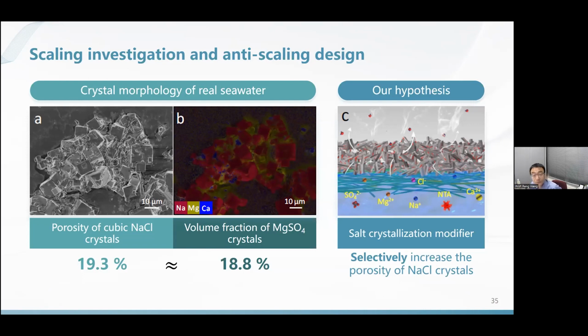I want to stress this. Our hypothesis might not be the right one, but our hypothesis led us to find a solution for this issue. So our hypothesis was this: because this is seawater, sodium chloride is a major component. We believe sodium chloride crystallized first. When it does so, it forms this porous aggregate with a porosity around 19%.